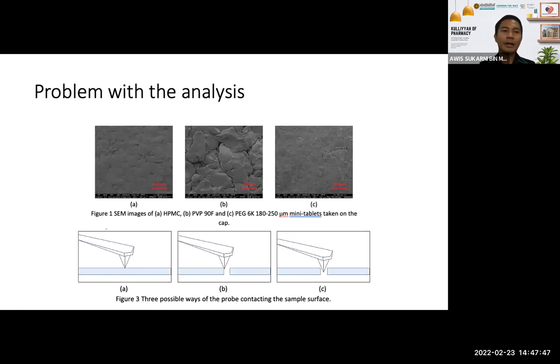After we got this result, we tried to figure out what the possible problem was that caused this to happen. We hypothesize it is because of the surface of the sample. This is the SEM image of the HPMC, PVP, and PEG. For the PVP especially, you can see there are a lot of gaps. You can see particles that have been compressed together, and it doesn't gel well compared to the PEG 6000 here.